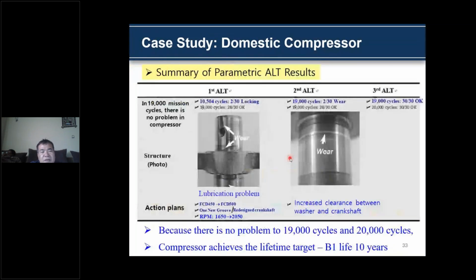This is a summary of the parameter ALT results. In the first ALT, we found a lubrication problem. In the second ALT, we found wear on the surface of the crankshaft. In the third ALT, there is no problem at 19,000 and 20,000 cycles. The compressor achieved the life target beyond 10 years.